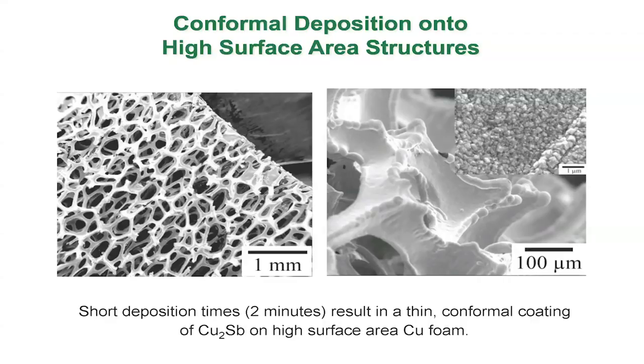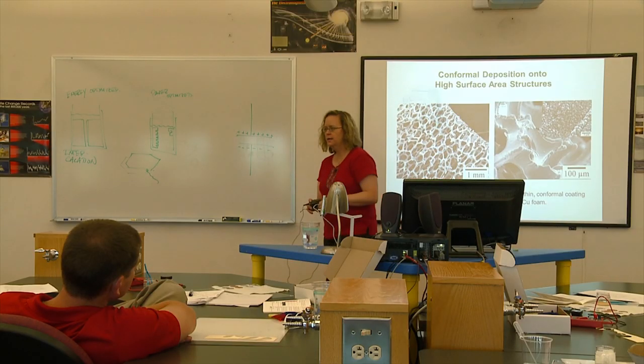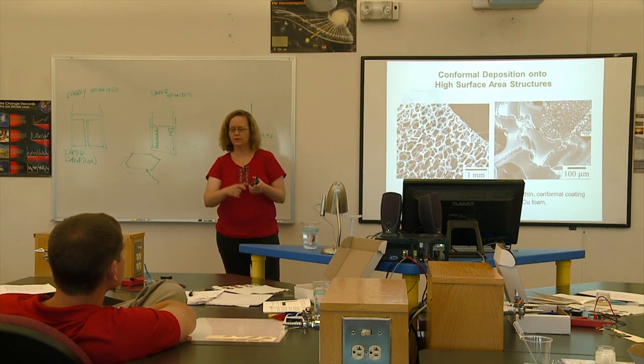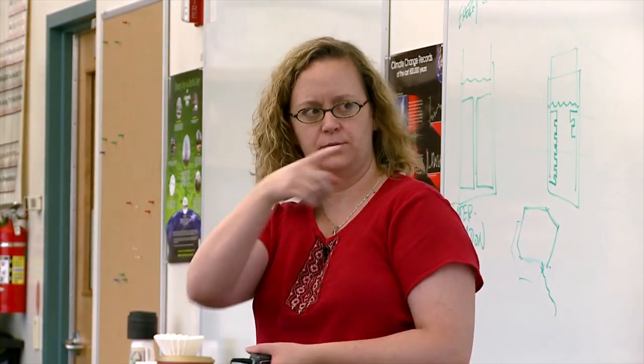This is what it looks like when we coat it on our foam. So this is what the copper foam looks like. A lot of the stuff we make is smaller than the wavelength of visible light, so we use a lot of electron microscopes. This is a scanning electron microscope image. This is 1 millimeter here. So low magnification image, and you could see all these big holes. If you zoom in, you can see that everywhere there was an edge, the copper antimonide plated faster. And that's really normal for electroplating. And then the flatter parts, if you zoom in even further, you see these tiny little cubes everywhere. That's the copper antimonide. And again, you take this copper foam that looks just like the copper discs you guys have. We put it in a water-based solution, 60 seconds, and it comes out purple, and that's what that is.